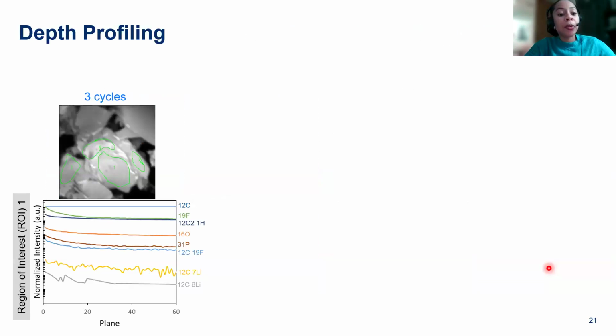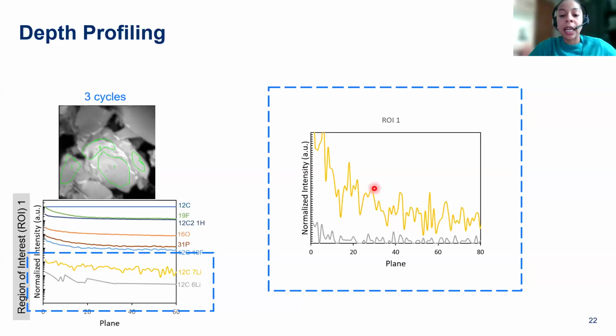And as I mentioned, we can do depth profiling, which is looking at how the signal intensity varies as we remove successive layers. Here we have a sample that's been cycled 3 times, and we're looking at just this region of interest on the basal plane, this nice flat graphite plane. We look at the normalized intensity on the y-axis, and the planes are on the x-axis. We see a decrease in the fluorine signal from the surface towards the bulk of the sample, and that's pretty much the same for most of the SEI components. If we zoom in specifically on the fluorine on a linear scale, we can definitely see that the decrease is more pronounced from the surface throughout the bulk of the material.